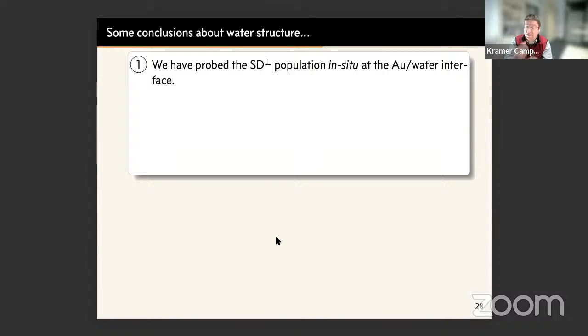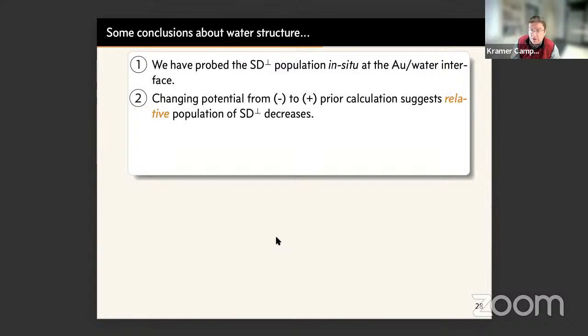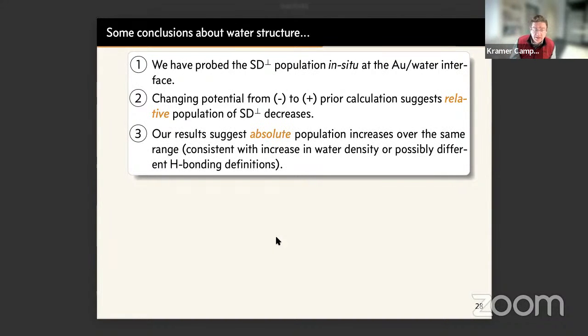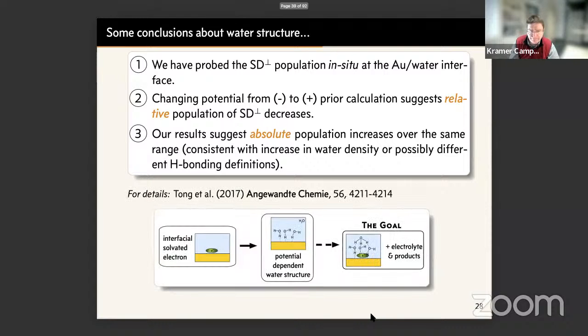So where does this leave us? We would say we have probed this perpendicular population in situ, operando, at the gold-water interface, changing potential from below the potential of zero charge to above. This is consistent with a scenario in which the population of this species is increasing. This is in disagreement with theory, which suggests that at least the relative population of this species decreases. So our results imply that the absolute population must increase over the same potential range, perhaps consistent with an increase in water density or somewhat different hydrogen bonding definitions as a function of potential.